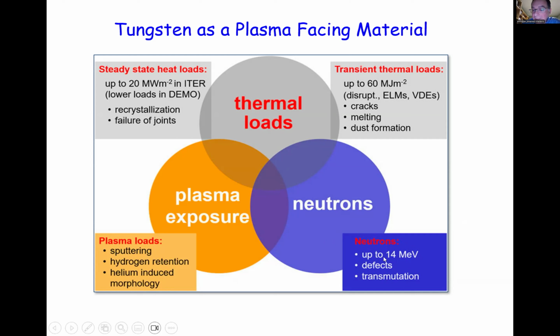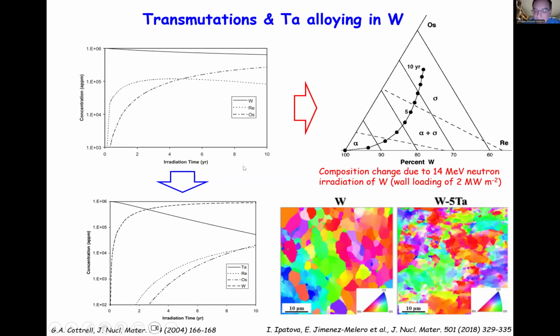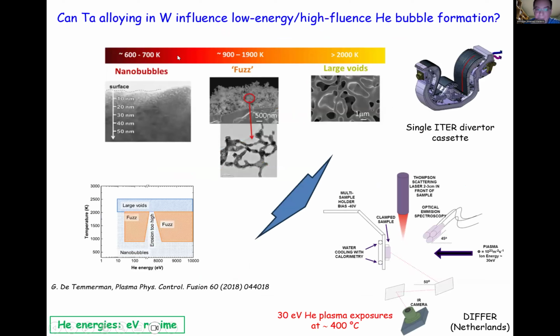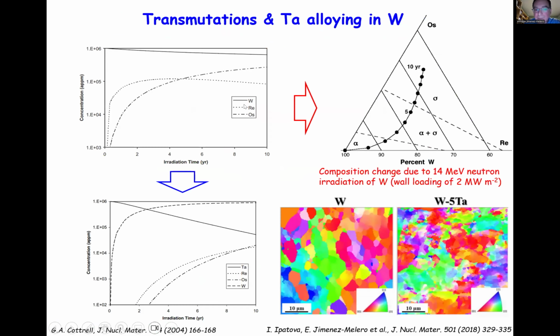They can cause lattice defects in the material, so they can displace atoms from their atomic positions in your lattice, and they can generate other elements which are not desirable by nuclear reactions. So if you start with tungsten, and we look at transmutation reactions, over time in the reactor, it will start to generate rhenium and osmium, and instead of having a pure tungsten tile or component, then you start to have tungsten-rhenium-osmium.